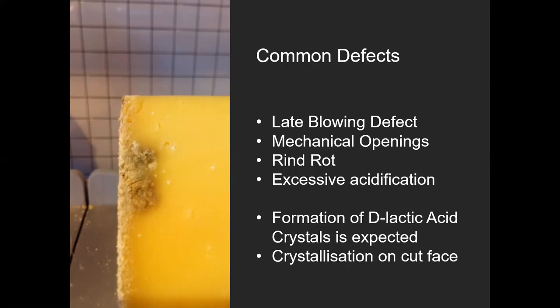Rind rot can be caused by soft curds around the edge of the cheese. The best way to avoid this is to ensure that each of the curds are treated to the same degree of heat treatment during the scald. If we're consistent in that and we're consistent in our size of cut, we shouldn't have excess acidity in some bits of curd compared to others. Excessive acidification is another common defect, and here we need to make sure that we've got those curds on the press before a pH of around about 6.3.